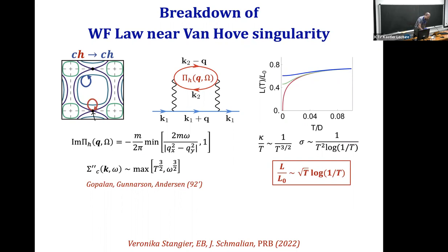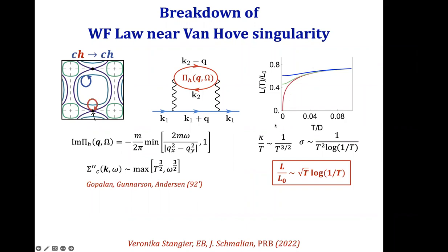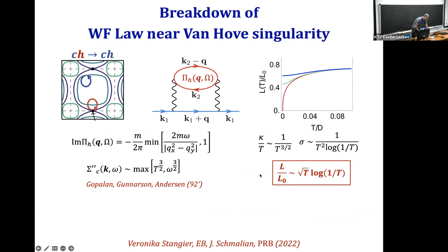Okay, so as a function of temperature, this is what happens. The red curve here is when our system is exactly at the Van Hove singularity. Okay, so there's this very dramatic drop of the Lorentz ratio basically to zero. And then if we tune away from the Van Hove singularity, this is what we expect. By the way, the calculation is for a perfectly clean system. We'll discuss what happens in the presence of impurities shortly. But in the clean limit, this is what we expect to find. This very dramatic violation of the Wiedemann-Franz law.